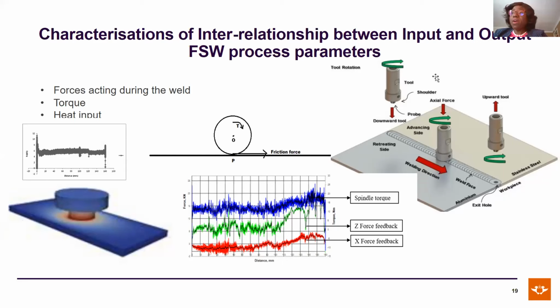We have the spindle torque data, and we are also able to calculate the heat input into the weld. The heat input into the weld is very, very important. It's a very important parameter, as it has been correlated to dictate the quality of the welds. So there are formulas available in the literature to calculate the heat input into